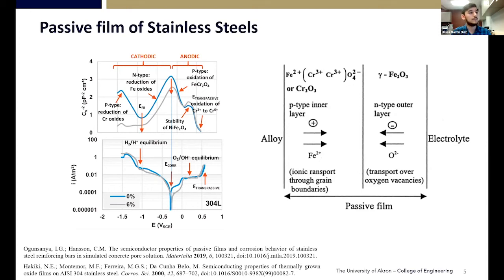As we can see in the image on the right, this exchange of electrons can be seen from the electrolyte, where the outer layer is mainly formed of the iron, which are the N-type, donating these electrons. However, towards the inside, in contact with the alloy, we have the chromium oxide, which are the p-type, and that give the passive film most of the corrosion protection properties.